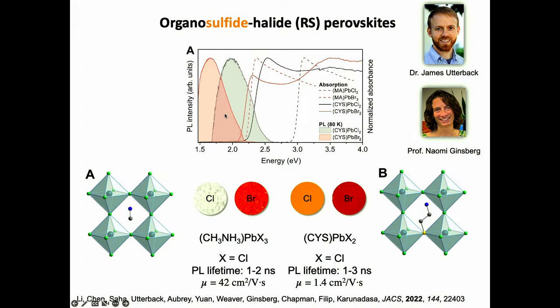We see very clear evidence that there is a trap state in this material. The photoluminescence has many of the diagnostics of a trap state. It is very weak, broad, and not quite at the band edge. And all of this, including this mobility data, tells us that there is some annoying trap state in this material. But if we could fix this trap state, and there are many ways to probe the trap states and try to fix it synthetically, these materials could be outstanding solar absorbers, which are much more stable than the halide perovskites.